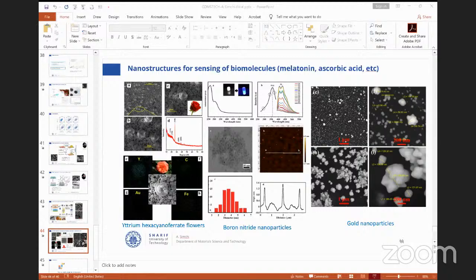In the second example, we used boron nitride nanoparticles. We developed a special procedure to prepare boron nitride nanoparticles and then cover the nanoparticles on the surface of three-dimensional graphene and use the system for detection of ascorbic acid, or vitamin C, in various products. The next stage is we used gold nanoparticles with various shapes, and we showed that this system can effectively be used for biosensing of many substances and biomolecules inside the blood or in water, or for water purification and so on.